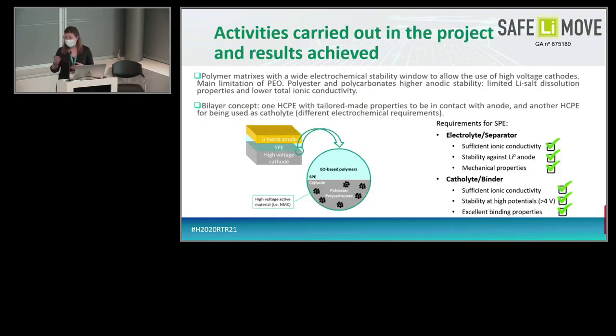As has just been presented, we are also working in SafeLiMove with a bilayer concept. If we consider the requirements of a separator or an electrolyte, we need to have high ionic conductivity, stability against the anode, which in this case is lithium metal, and also good mechanical properties. Now if we move to the cathode side, the requirements are slightly different because we need to work at high voltages, so we need to have a high anodic stability. Of course, again, enough ionic conductivity, and in this case, we need to have good binding properties.